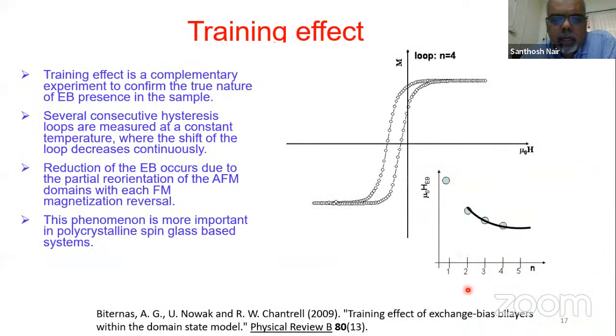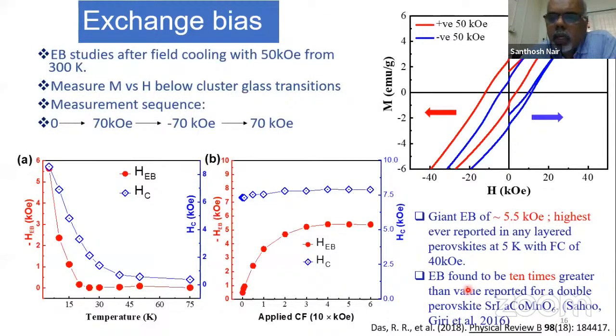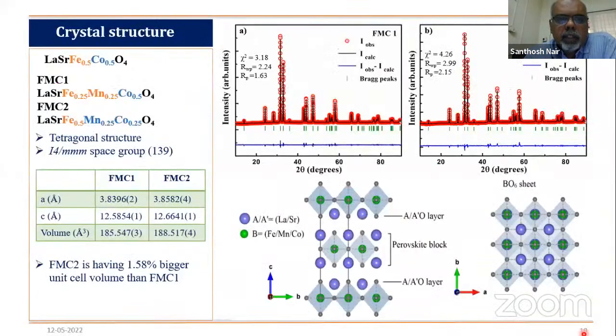Thank you. So the details of this work can be seen in the publication by Ranjana, my student, in PRB 2018. As a continuation of this, we took another system, lanthanum strontium, where instead of manganese you have iron. The parent perovskite compound is not actually a ferromagnet; it's more of an antiferromagnet or even glassy. But we don't see any exchange bias in there.